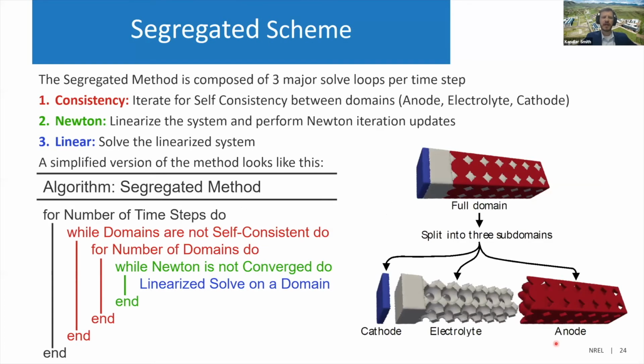And our method that we are solving here, we've done some work to directly solve all 3 domains simultaneously, the cathode, electrolyte, and anode. For us, it turned out the best, the most stable algorithm, as well as the fastest, was to do a segregated solve. So here we are solving each domain separately. That's a linearized solve on an individual domain using the Newton method to converge. And then we have an outer loop of iteration to go until all 3 domains are self-consistent and everything is conserved.